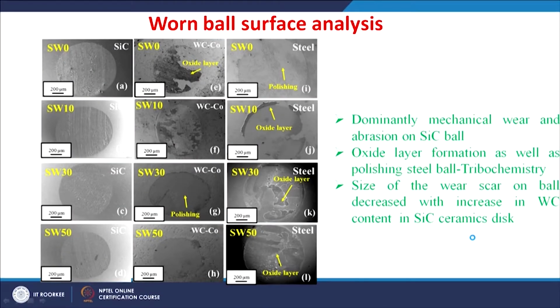worn surfaces. So, you can see the counter body which is a steel. So, the impression is a circular impression after the wear. The size of the wear scar on the ball decreases with the increase in the tungsten carbide content in the silicon carbide ceramic disc. So, dominantly there is a mechanical wear and abrasion on the silicon carbide ball, whereas oxide layer formation as well as the polishing is observed against tungsten carbide or on the balls of tungsten carbide or the steel. So, the ball surface analysis shows the presence of the tribochemistry on the tungsten carbide cobalt balls or the steel balls, whereas the silicon carbide balls, they do not show any tribochemistry. It is simply the fracture, or you can see the abrasion and then removal of this material by fracture.